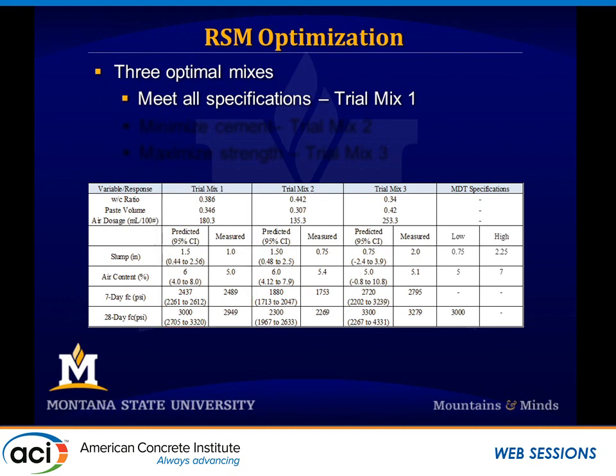So then we said, all right, let's play with this a little bit. One thing to note about this, 0.386 water cement and a paste volume of 0.346, this amounts to about a 7-sack mix. So if you're familiar with concrete mixes, a 7-sack mix is pretty rich, right? Actually very rich for a concrete pavement. I think they're usually on the realm of around 5.5 to 6.5 sacks of cement per yard of concrete. So this is a pretty rich mix.